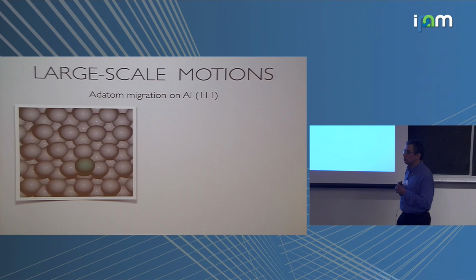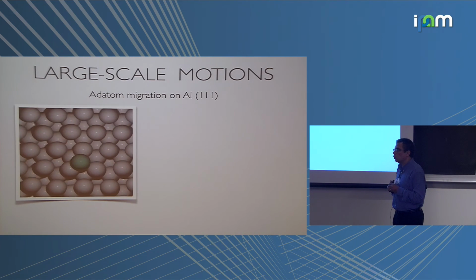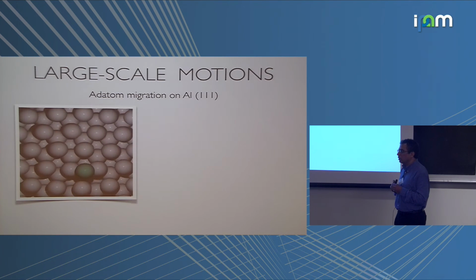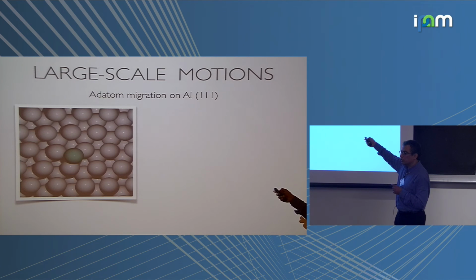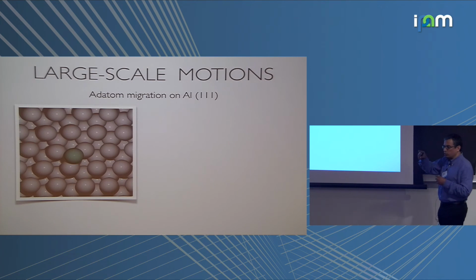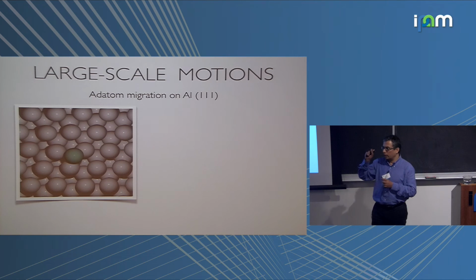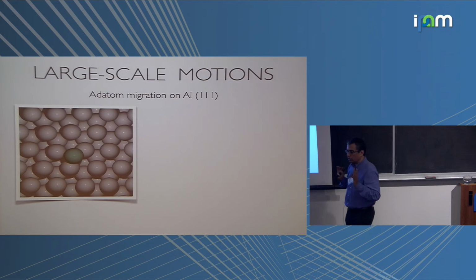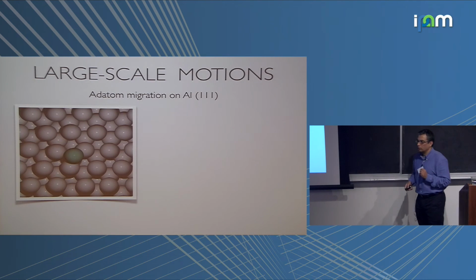Isn't this a famous example where the atom should sink into the surface to do the exchange? Aluminum is famous because people were trying to compute the diffusion barrier with this process, and they could never match the experiment until they found out that the way it diffuses is by exchanging with the surface. Is it for the 111 surface? I'm not 100% sure. I do recall what you're saying, but I don't think it's the 111 surface, but I need to check. Yeah, 100.